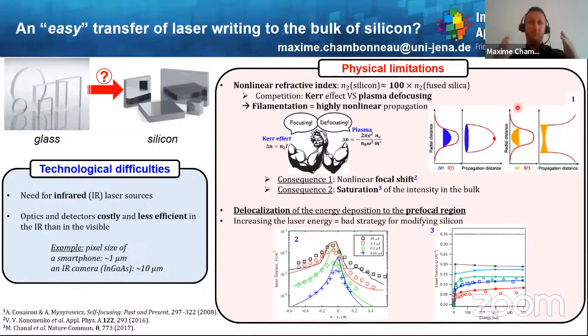However, when the beam is focused inside the material with a very tight beam size, a plasma will be formed. So you ionize the material, and this ionization results in the plasma defocusing phenomenon. So you create a population of free electrons inside the material, and this will defocus the beam. So in the end, you will have those focusing and defocusing dynamics near the focus, the hypothetical focus at least. So this is what we call filamentation, which is a highly nonlinear propagation regime.